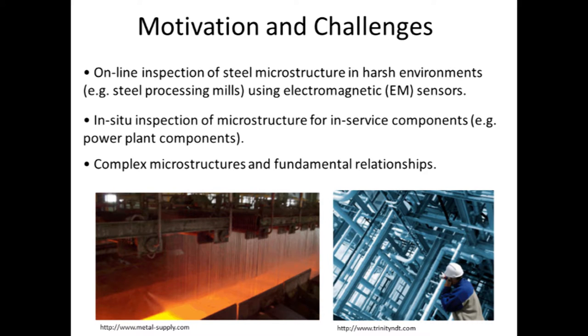In terms of the motivation and challenges to move the field of non-destructive evaluation forward, we have several aspects. There's a need and desire to do online microstructural assessment, because we can't do metallography — you can't stop the mill halfway through and look at the hot microstructure dynamically. So there's quite a lot of desire to not just infer microstructure through modelling and temperature information, but to get some kind of direct measure. There's also desire for in-situ inspection — at the moment it may be inferred from hardness measurements or replicas, giving surface-dominated information, when you might want to look deeper into the material. And ultimately, wouldn't it be nice if we could measure all microstructures in complex materials non-destructively?